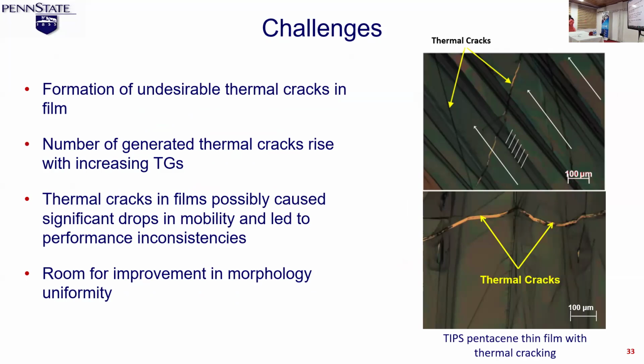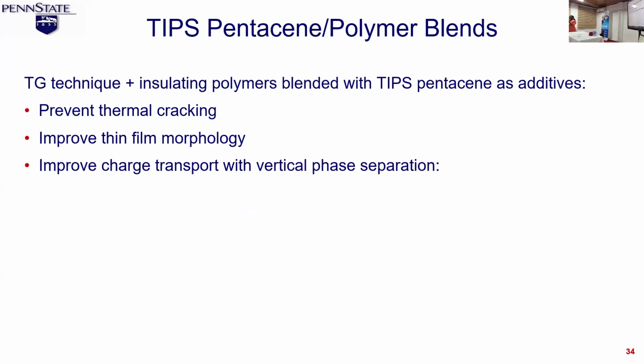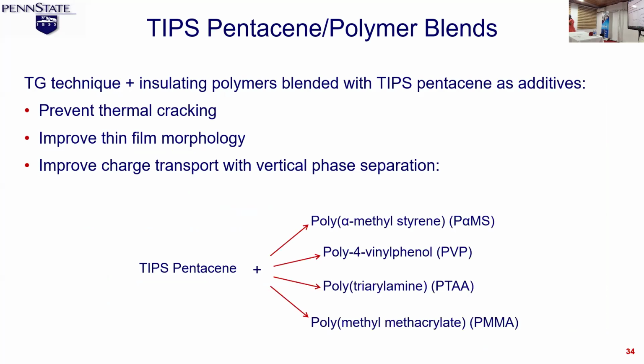So then I had to try to figure out what will prevent these cracks, and that's where the blend method came in. So adding a polymer to the solution, because that would allow flexibility. So when the film develops, you don't get cracks in it. And I tested 4 different polymers. The best one was the top one, which is the PαMS, poly alpha methyl styrene polymer. All these chemicals have long names, so we just abbreviate them.